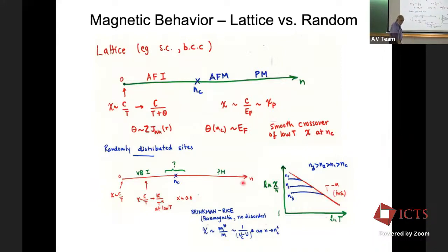And so the question, how do we match this constant susceptibility for a Pauli metal with this diverging susceptibility of the insulator? And one might think, all right, that maybe what you have is a susceptibility that actually is temperature dependent at high temperature. And then depending on how far you are from the metal insulator transition, it becomes constant at low temperatures. And so in this case, I've drawn three densities, N1, N2, and N3 that are above the metal insulator transition, where N3 is greater than N2 is greater than N1. So basically, you're trying to somehow smoothly cross over from the insulating behavior to the metallic behavior. And that was originally the idea we had,